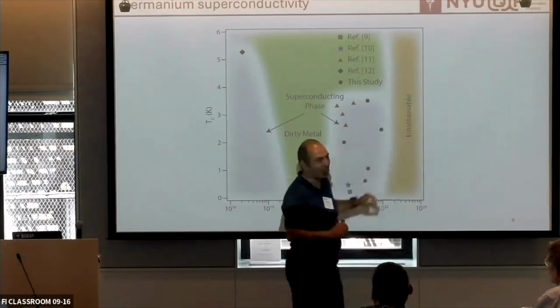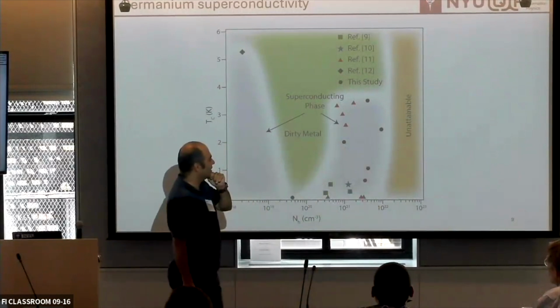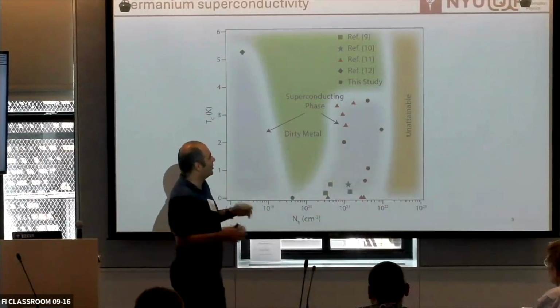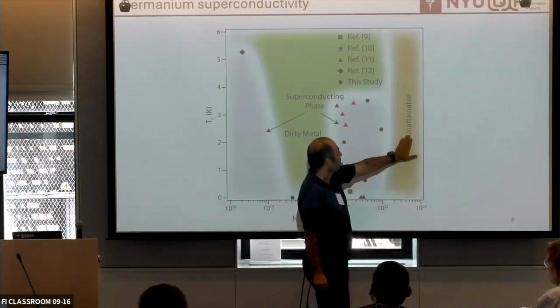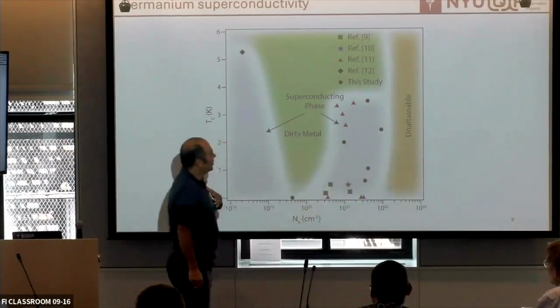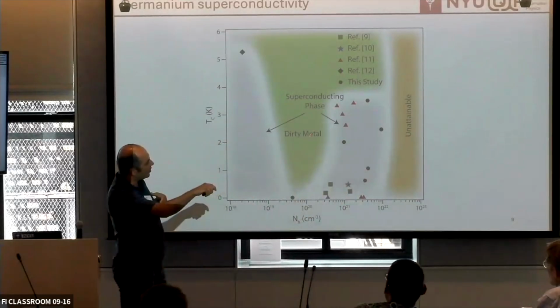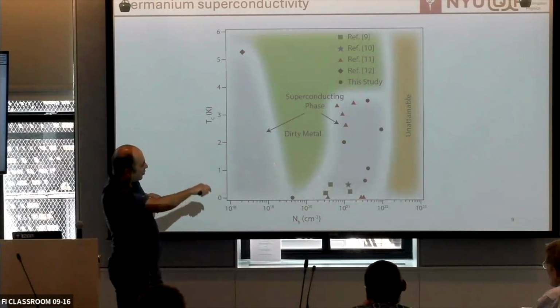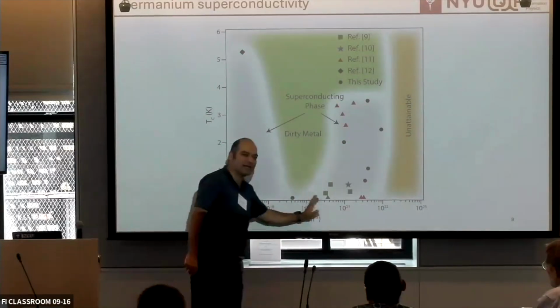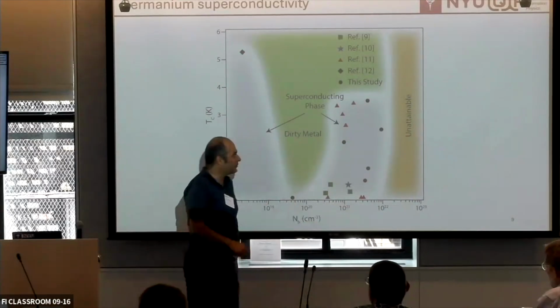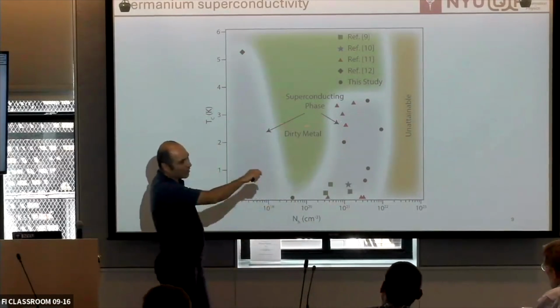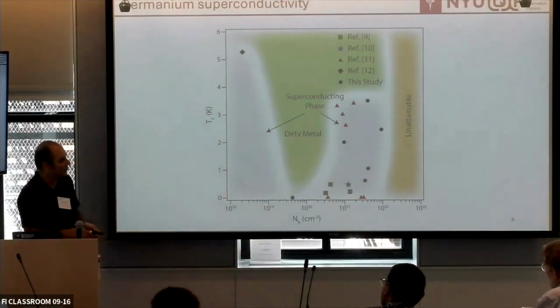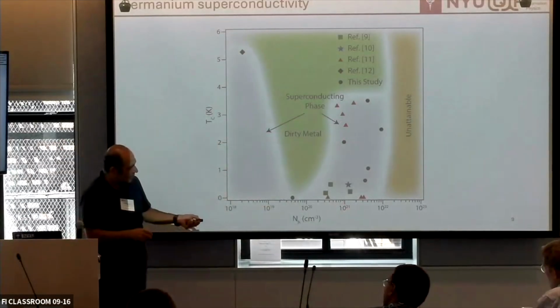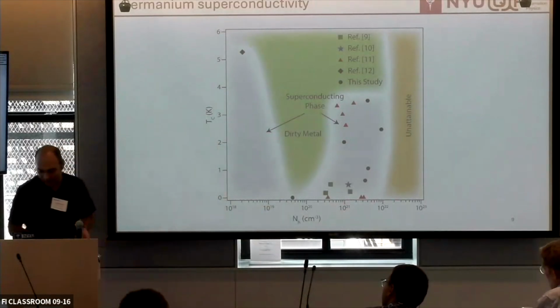And that's why I don't know exactly, probably the fields are too strong and we can probably calculate this. But this is kind of in contrast to everything else that had been done before that basically could not make the barrier of the 10 to the 20. And for the first time now we can get a few Kelvin TC at the level of normal electrons and disorder, right? So we are very excited about this.